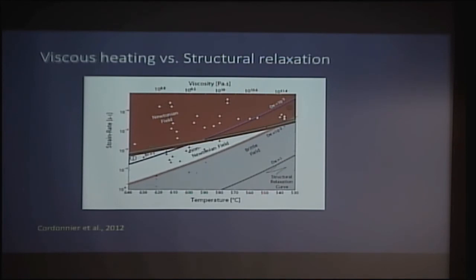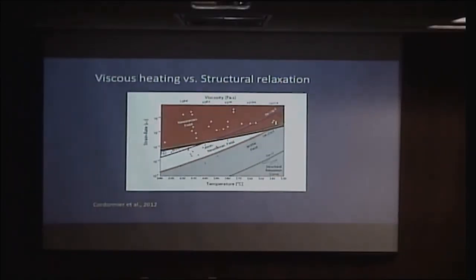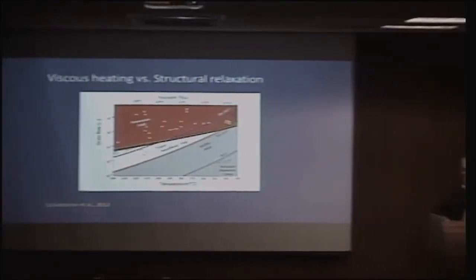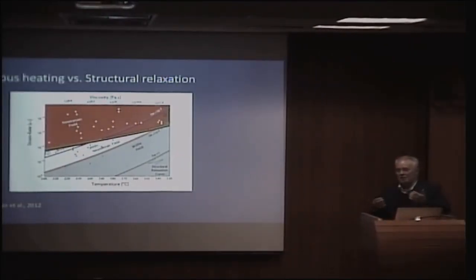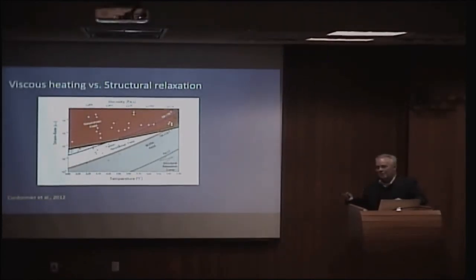The crossing of these two lines divides a regime where you will heat them first as you accelerate the deformation, which will make you avoid explosions, because as you heat them up, the viscosity goes down, and you drift back away from the glass transition, from this ugly fate awaiting you. Or you're on the other side of the crossover, where they will fail before they start to heat, because they scale differently in strain rate. It's a beautiful interplay of two possible fates of volcanic systems.